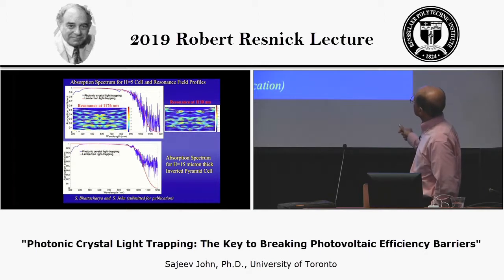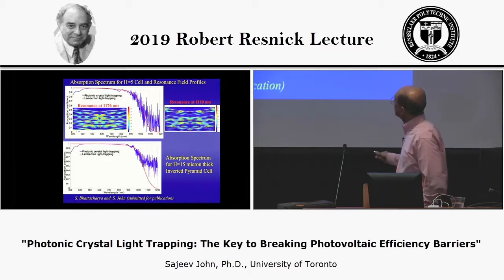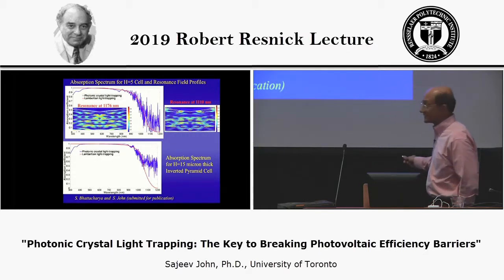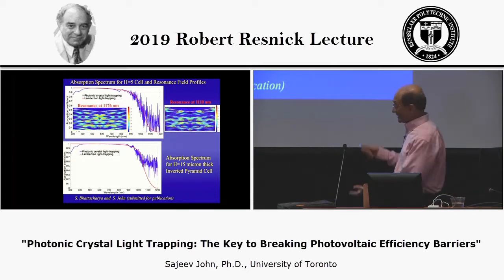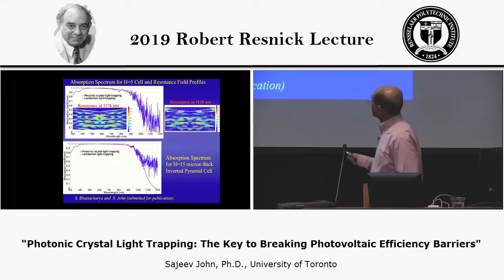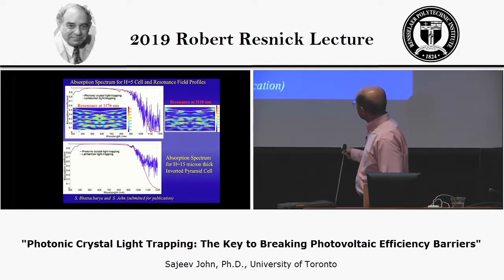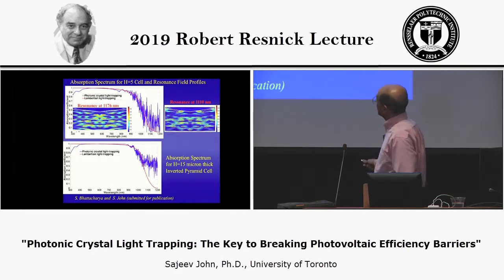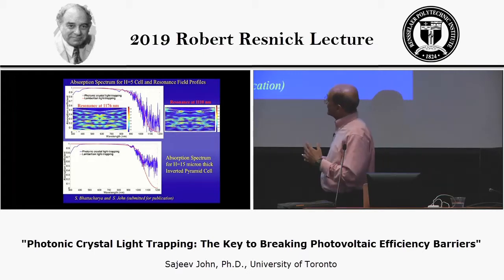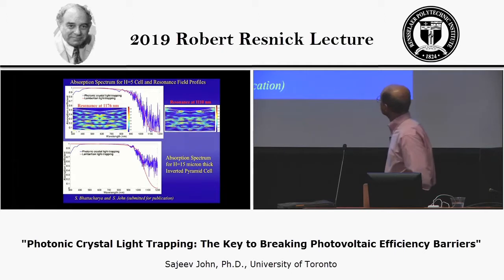You see a lot of resonances and wave interference effects going all the way up to 1200 nanometers. This is the 15 micron cell. This takes an enormous amount of computational time to simulate a large structure like this. But you see that it's well above the Lambertian limit, which is shown in the red curve here. And of course, the Lambertian limit ignores any specular reflections, so that is always ahead of us in the shortest wavelength limit.